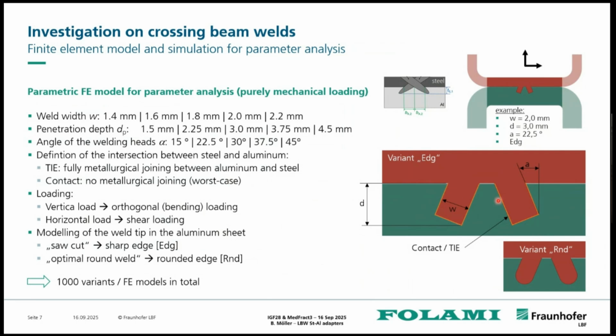We need to decide whether there is more a contact between these two materials, or if there is more an ideal tie, which would mean that we have a fully metallurgical joining between the two materials, which is never perfectly the case. However, contact would be more or less the worst case scenario over here. And we have the two loading directions, which I explained before.